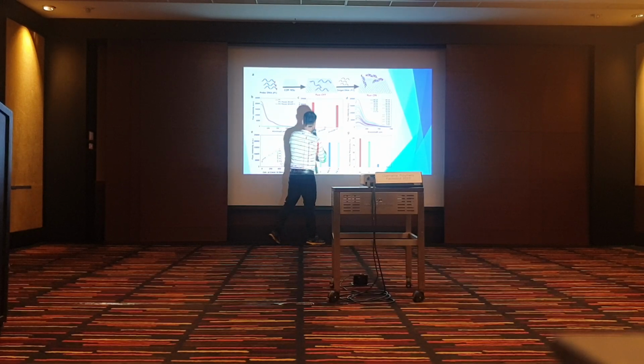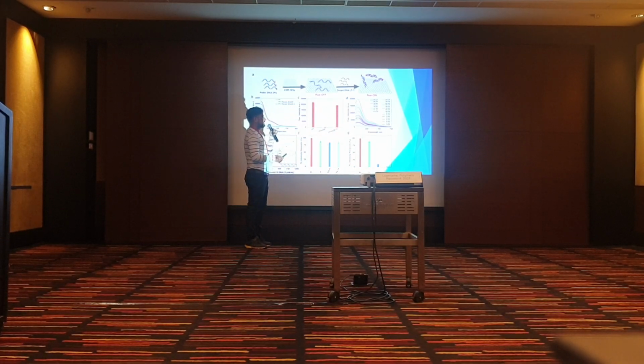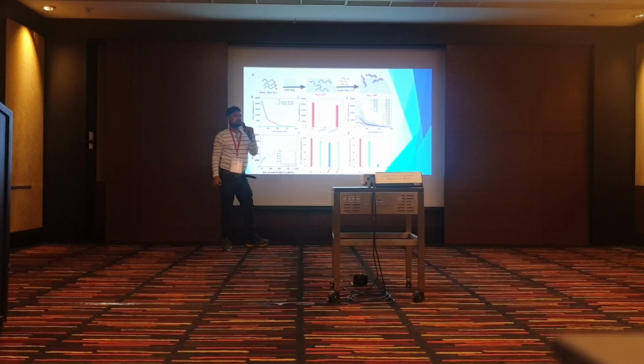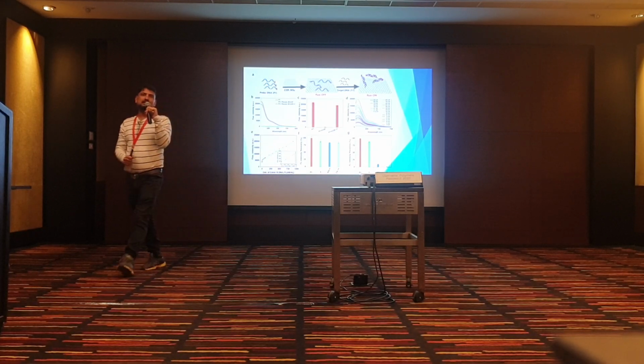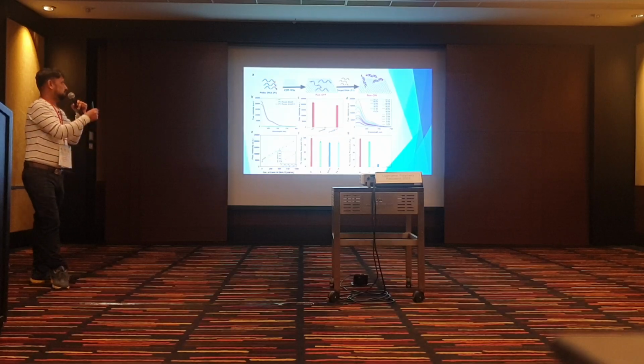After decreasing when we put our material, it is decreased, but when the target is there, it increases again. The single mismatch DNA gives very little, and when the random DNA comes, it does not give any response. This means our material's selectivity is very high. Only the particular disease we can detect through this detection method.